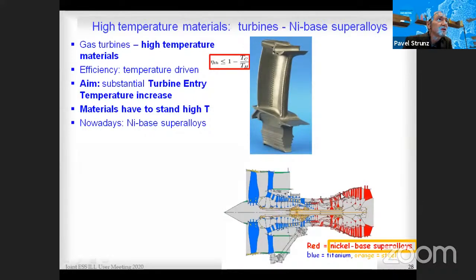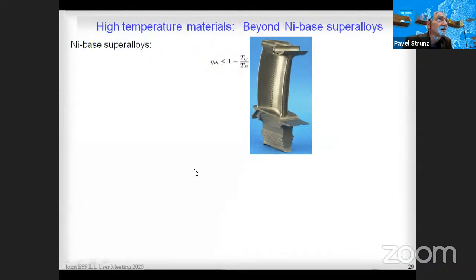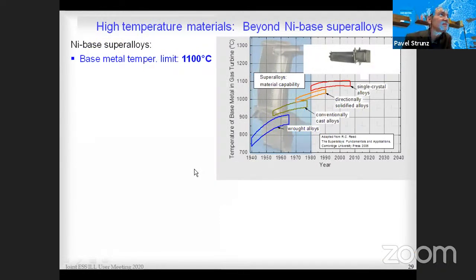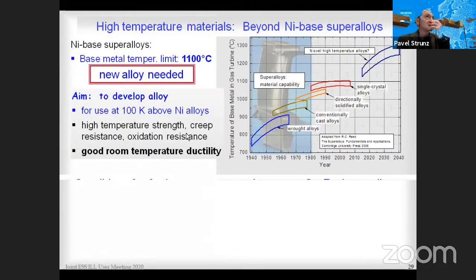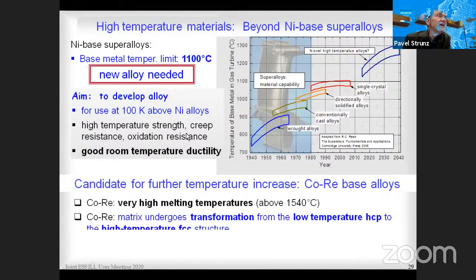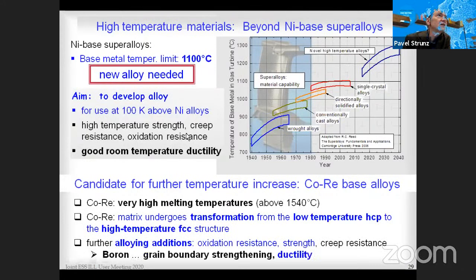Materials in the high temperature part of the turbine have to stand the high temperatures, for example these turbine blades. And nowadays, mainly nickel-based superalloys are used for this purpose. However, nickel-based superalloys are at their base metal temperature limit. They are at the end of their possibilities, and this limit can hardly be exceeded. So we need to look for another material. The aim, in the first step, is to find an alloy which is able to be about 100 kelvins above the nickel-based superalloys. A good candidate is cobalt-rhenium alloys.